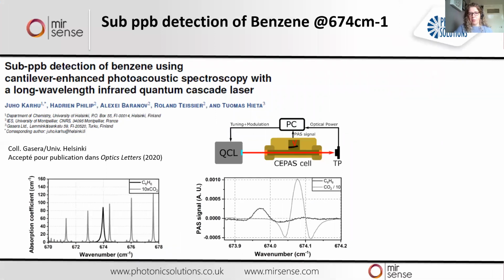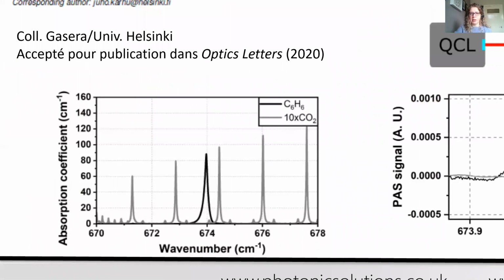I touched on this briefly, but these lasers have been used to measure sub-parts per billion levels of benzene. This is an outstanding result, and it was achieved by the Gasera company in collaboration with the University of Helsinki, based in Finland, and they were detecting benzene at 15 microns using a cantilever for photoacoustic spectroscopy. If I zoom in again, the benzene peak at 674 centimeters to the -1 was clearly detected. This technique worked extremely well, and the group was able to get a limit of detection below 1 part per billion.